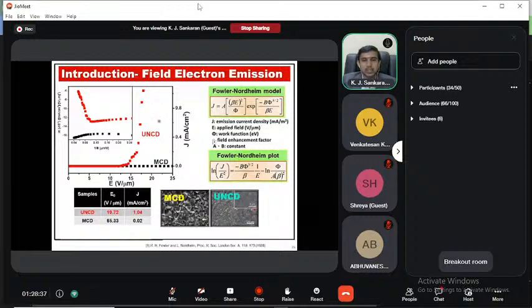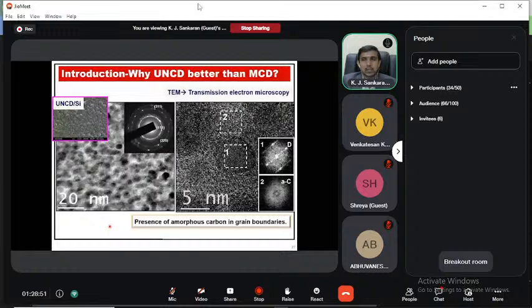Here you can see that UNCD, with smaller grains, has a low turn-on field of 19 as compared to the microcrystalline diamond material, which has a turn-on field of 65. To know the reason why UNCD is better than MCD, TEM plays a key role. The HRTEM result shows that region 1 here is the UNCD material, in which smaller grains of 5 nanometer size are surrounded by amorphous carbon materials. So the amorphous carbon surrounding the UNCD grains makes electron transport easy, making it a very good field electron emission material.